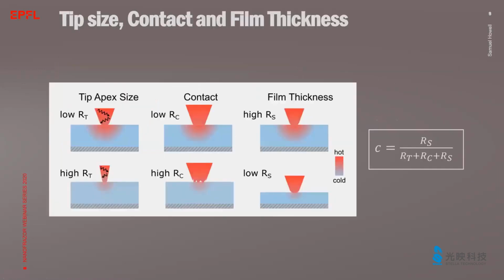Let's have a look at how the tip size, the tip-sample contact, and the film thickness affect the temperature. Due to the small size of the tip towards the end, the heat flow is reduced. This is because the tip dimension is smaller than the mean free path of phonons.